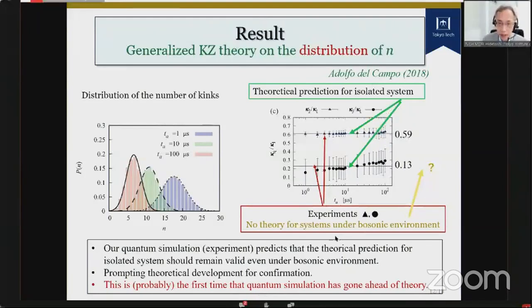But we don't have a theory for systems under a bosonic environment. So we expect from this experimental finding that the theoretical prediction for isolated systems should remain valid, at least to a good extent, even under a bosonic environment. This prompts a theoretical development for confirmation, a theory for systems under a bosonic environment. And we think this is probably the first time that quantum simulation has gone ahead of theory. So this, we believe, is remarkable in this sense.